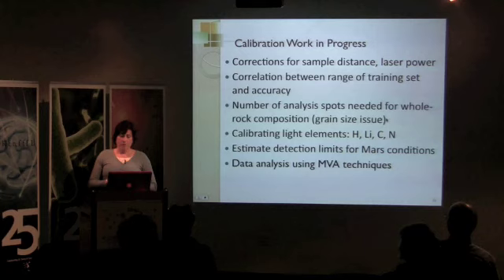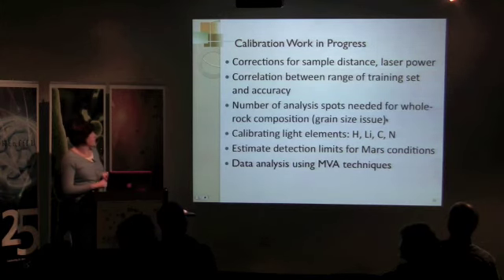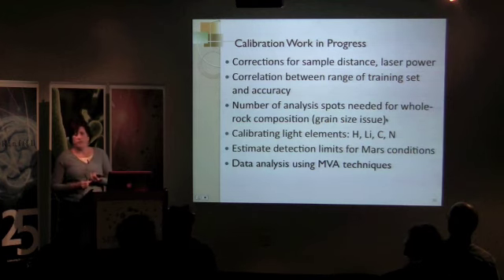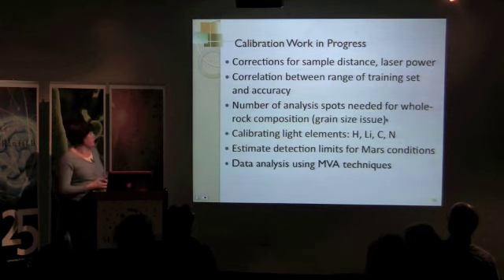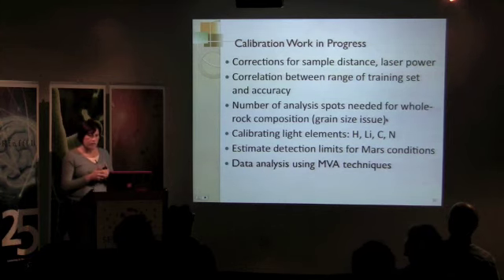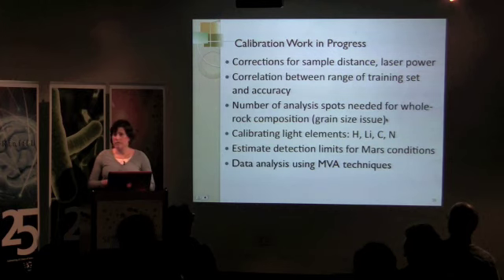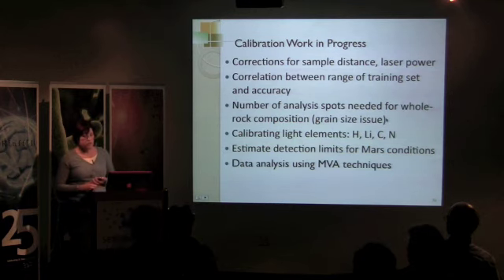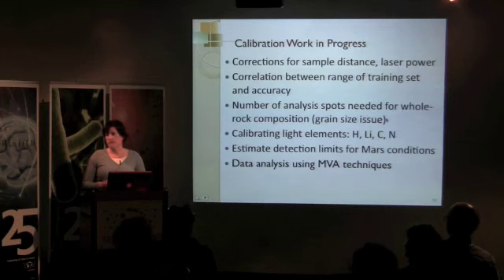We have a lot of ongoing calibration work in progress, and these include trying to establish correlations between sample distance, laser power, and signal intensity, and also make correlations between the range of our training set of standards and the accuracy that we get with ChemCam. We're also experimenting with the number of spots we might need to get a whole rock analysis using samples of different grain sizes, and also trying to push the envelope for our sensitivity to light elements. This requires testing different types of multivariate analysis to see what might give us the best yields, and trying to estimate overall detection limits for Mars conditions. And as I mentioned, we're trying to apply different multivariate analyses and see which ones will give us the best results for our ChemCam data.